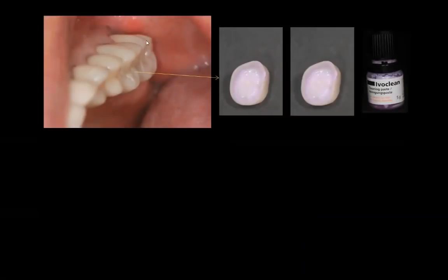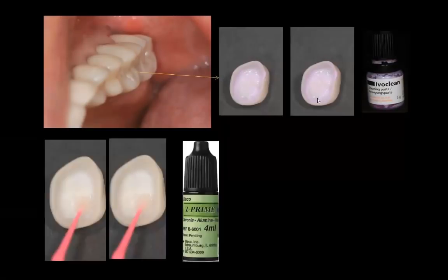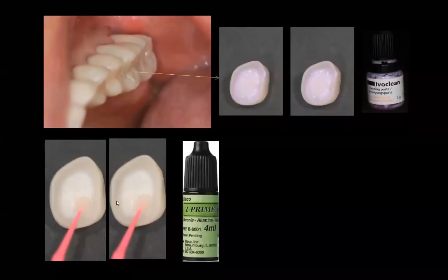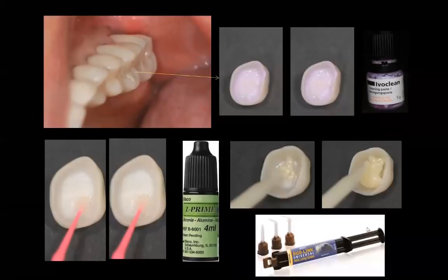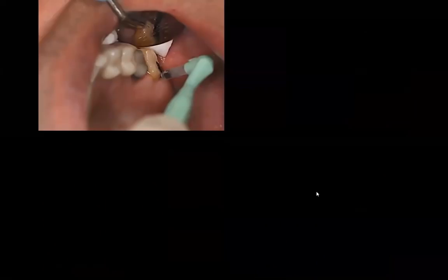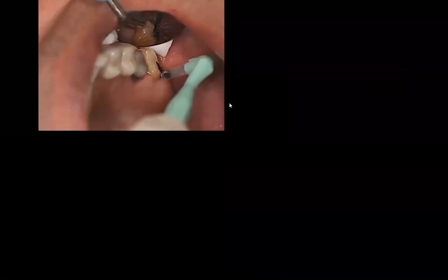If you have a non-retentive second molar, clean it with Zirclean. This is Ivoclean, or you could use Zirclean. 30 seconds, rinse it out and dry it. Here's our Z Prime Plus. We're applying our ceramic primer. Let that sit for about 30 seconds and dry that. And then my assistant places dual cure resin cement in the crown. Boom, seat the crowns. Here we are treating the teeth just like before.